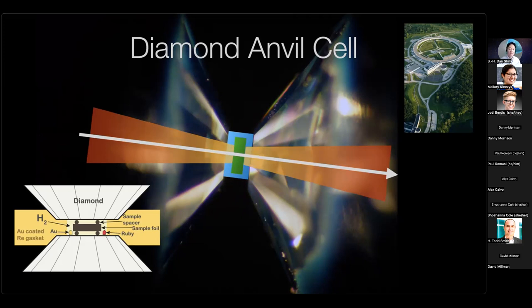What's nice about using diamond as an anvil material is that it's transparent to a wide range of electromagnetic wave ranges. So we can bring in infrared laser and focus them to the sample immersed in the hydrogen, and we can melt the silicate and metal samples. At the same time, if we conduct this experiment at synchrotron facilities where intense X-ray beam is available, we can monitor the type of chemical reactions and materials formed during the chemical reactions.